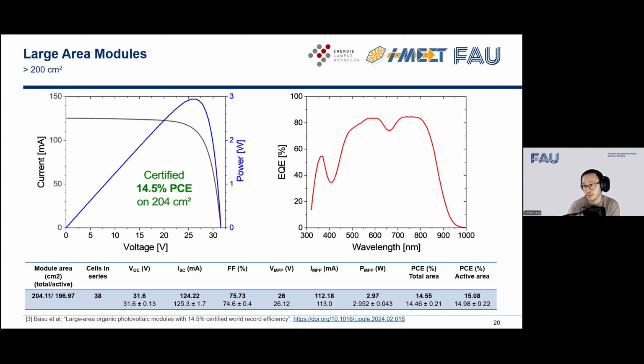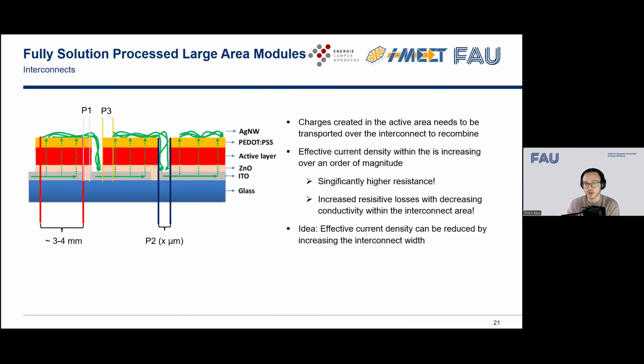So how does it go for nanowires? Here, the interconnects are a little bit different because now we have nanowires rather than evaporated silver, and nanowires are not as conductive as evaporated silver. So what you have to know about modules to understand the following is that all of the charges that we create within the active area have to be transported in the interconnect. So you have an effective current density in the interconnect that is a lot higher compared to the active area. That means that you need a quite high conductivity to get efficient recombination in there.